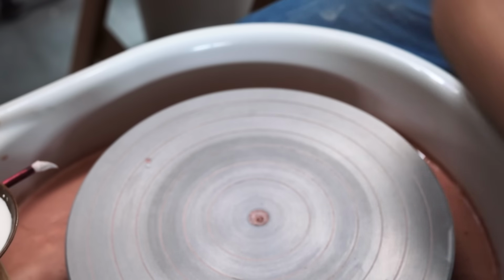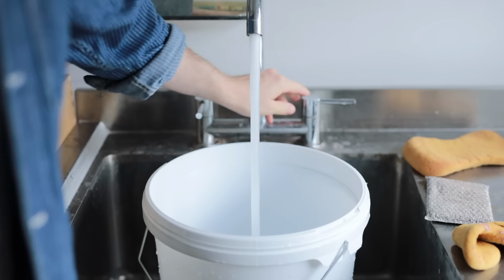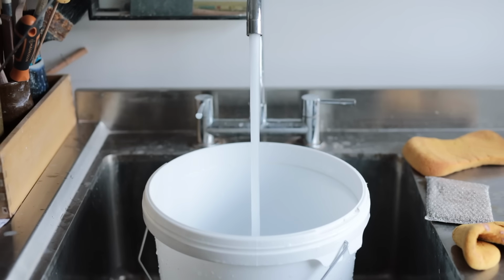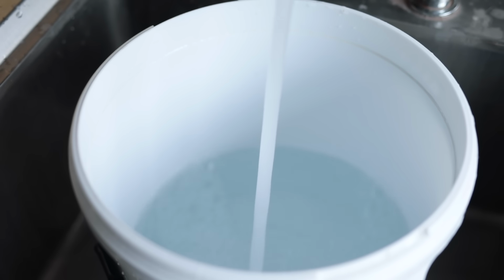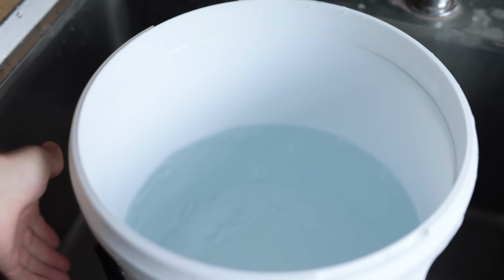Now, I'm going to be using a new glaze for these pots, so I thought I'd take you through the process of how I mix up one of my glazes. This will be the bucket that the final glaze goes into, so I fill it about halfway up with water, and then I pour this water into a larger bucket, and it's in here that I'll measure out all the raw materials and do the mixing.